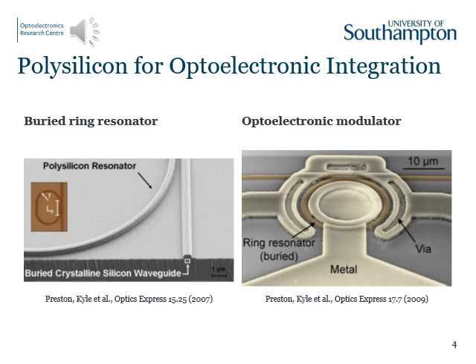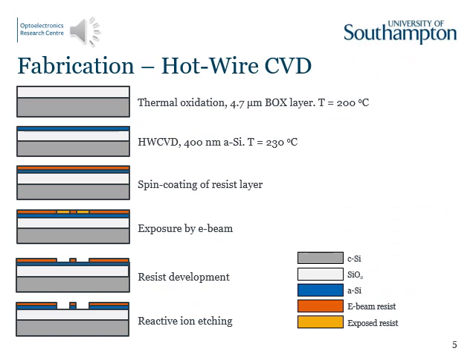However, linear losses remain high as a consequence of the small grain size, which results in a high amorphous fraction, causing absorption at telecommunications wavelengths. Our work has focused on the minimization of optical losses.